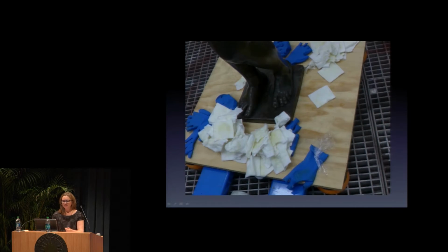And the idea of using solvents to remove the Incralac and all the waste just did not appeal to me at all. So I do know when we worked on the bronze form, I had a lot of coupons made up with aged Incralac, and I was able to remove it without any chemicals, and just on coupons. And so that gave me the idea that, well, I think it's possible. I'm sure that if we use carbon dioxide, we can find a way to make it work.